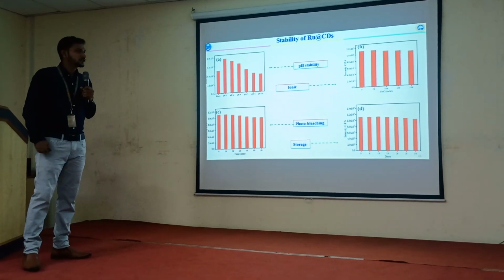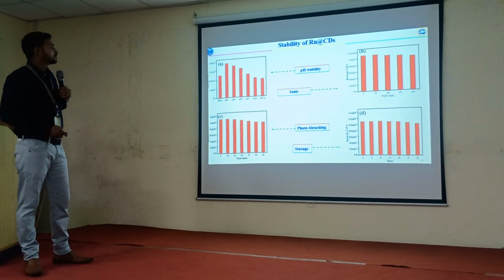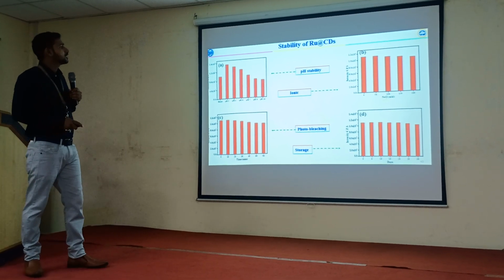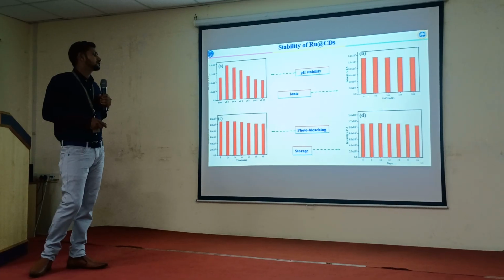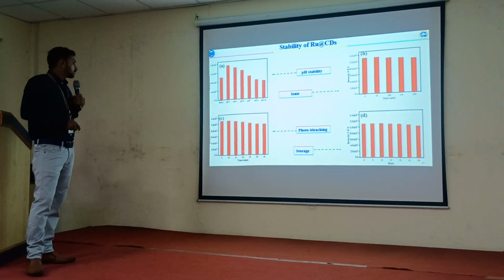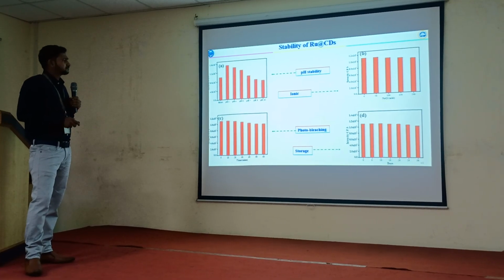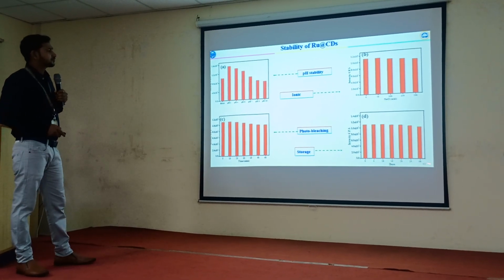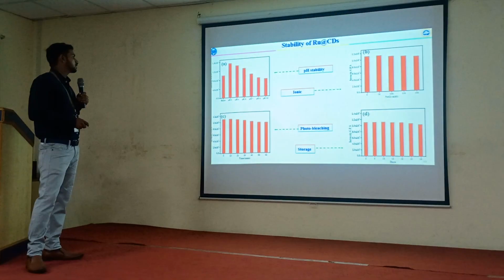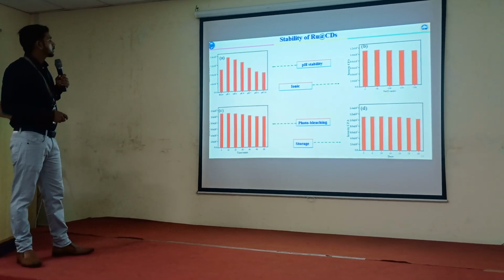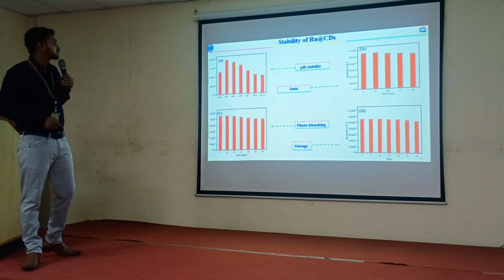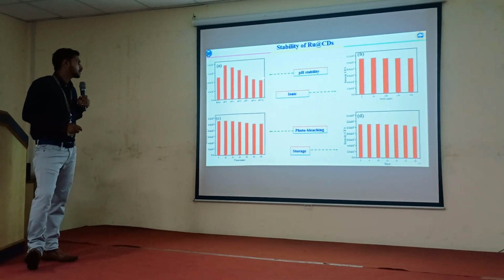And the stability of the ruthenium carrying carbon dots was further evaluated. The ruthenium carrying carbon dots show very good stability under ionic concentrations from 0 to 200 millimolar of NaCl, continuous photo irradiation of 60 minutes, and a storage time period of 0 to 30 days. But under pH conditions, at alkaline pH, the carbon dots show a reduction in PL intensity, which may be due to the ruthenium 2+ in the carbon dot matrix being converted into nanoparticles at alkaline pH.